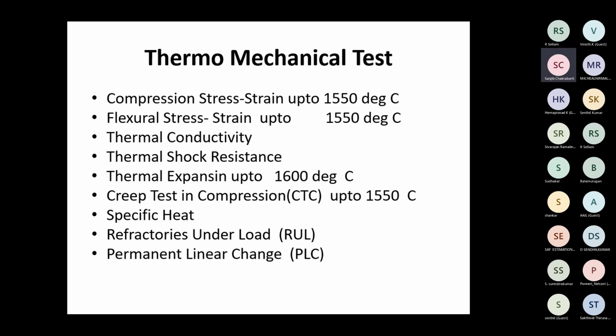Thermal conductivity, flexural stress strain, thermal shock resistance, thermal expansion, creep test in compression up to 1550 degrees centigrade, specific heat. Refractoriness under load, RUL, a very important test. Because all refractories, when stacked in a furnace, are under load. One refractory is above another refractory, so they are under load.